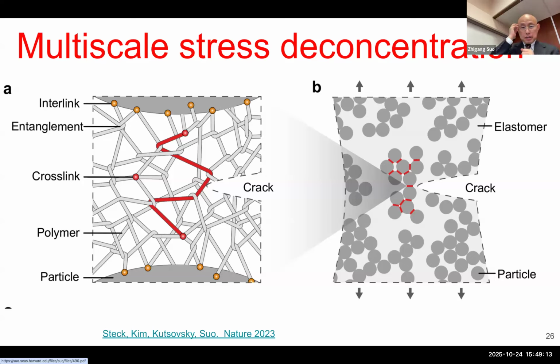So here's the idea, the conclusion we found. We have these chains. Here's one particle, here's another particle. In between the particles, you have rubber. This rubber, we made have enormous long chains, not natural rubber, synthetic rubber in our case. As we already know, when a crack comes along, the high tension at the crack is transmitted to the entire strand. If your strand is long, you dissipate a lot of energy. That was our initial thought.